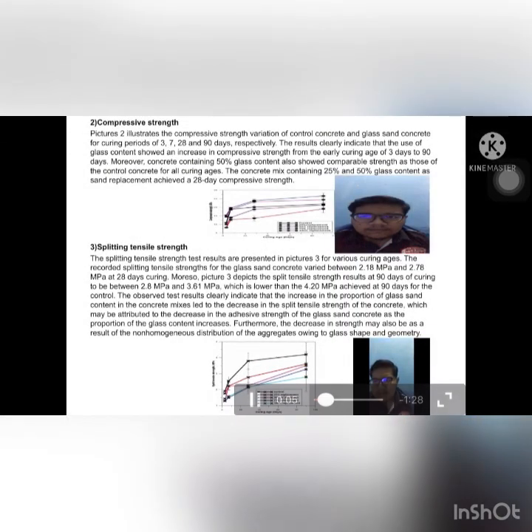Last, splitting tensile strength. The splitting tensile strength test results are presented in Figure 3 for various curing ages. The recorded splitting tensile strength for the glass sand concrete varies between 2.18 megapascal and 2.78 megapascal at 28 days curing. Moreover, Picture 3 depicts the split tensile strength result at 90 days of curing to be between 2.8 megapascal and 3.61 megapascal, which is lower than the 4.20 megapascal achieved at 90 days for the control.